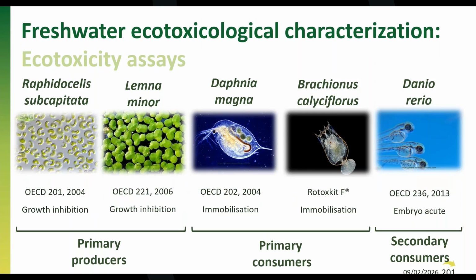However, when running then the LCA, the framework recommends to use more species, because different species may hold very different sensitivities to the different chemicals, and so we need to be representative of the natural communities. In this sense, we decided to test 5 species that are here represented. So a microalgae, an aquatic macrophyte, the Daphnia magna already mentioned, then another primary consumer that is the rotifer Brachionus calyciflorus, and then Danio rerio that is the fish species. So for each one of these species, we tested the 5 concentrations of all the raw materials, the bio-based materials, and the intermediate formats that I mentioned earlier.